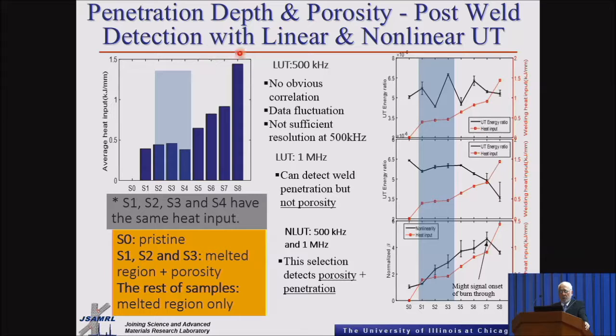What happened to the porosity? One of the problems that we have with the porosity was when we used linear ultrasonics. We looked at these welds that were fabricated using different heat inputs, so you increase the heat input. These three welds in here were fabricated using the same heat input. The only difference is we changed the amount of porosity. S1, S2, S3, and S4 are the ones where the heat input was the same, and we changed only the amount of argon, 2% oxygen that we had.